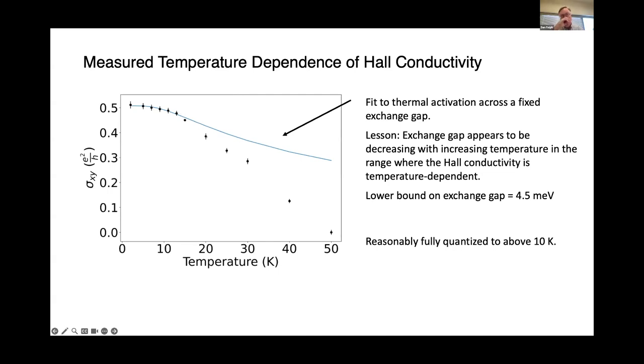The temperature dependence here doesn't correspond to just thermal activation across a fixed exchange gap. We think what's going on is that the exchange gap is decreasing in the range where the Hall conductivity begins to decrease too. But from the temperature dependence, we can set a lower bound on what the exchange gap is of about 4.5 meV. And that's a lower bound because likely even where we're starting to see a little bit of change around 10 Kelvin or so, likely the exchange gap is a little bit lower than what the zero temperature value is. But this again is a factor of 100 larger than what's been seen in terms of a quantized value for any deposited proximity effect structure, and even a little bit higher than what's seen for magnetically doped topological